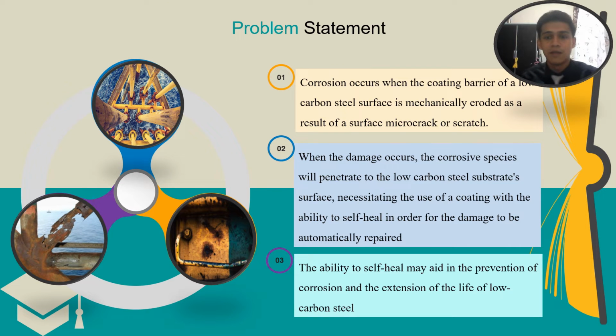And for the problem statement in this project 1, metal corrosion is primarily caused by two factors, which are the material and its surrounding. The corrosion occurs when the coating barrier of the low carbon steel surface is mechanically eroded as a result of surface microcracks or scratches. When the damage occurs, the corrosive species will penetrate to the low carbon steel substrate surface, necessitating the use of a coating with the ability to self-heal in order for the damage to be automatically repaired. And the ability to self-heal may aid in the prevention of corrosion.